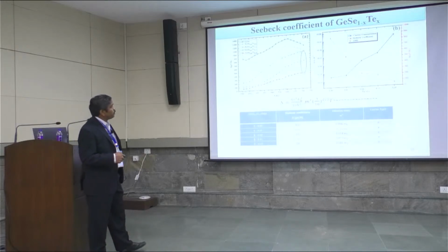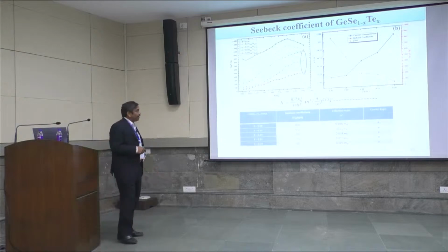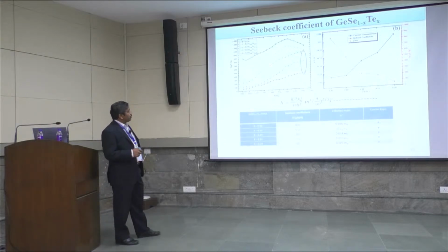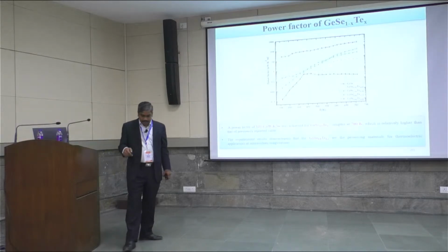And the Seebeck coefficient of this sample, which was compacted by a hydraulic press, was measured using the Seebeck measurement system. And the Seebeck coefficient is quite high for the pure system because of its highly resistive nature. Whereas when the tellurium content increases, the Seebeck coefficient decreases as a function of tellurium content because of the variation in the resistivity of the sample. And this is the relation between the Seebeck coefficient and the carrier density, and that obeys the Pisarenko relation, as they are inversely proportional to each other, and that gives the reliability of the measured data. And the variation of the Seebeck coefficient is in accordance with the resistivity variations.